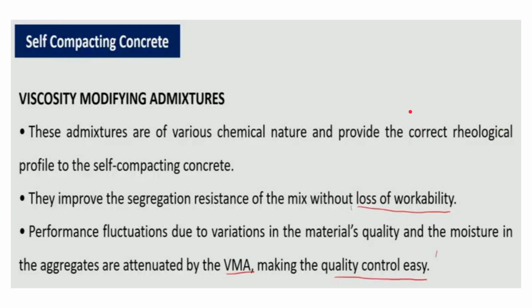Apart from that, let us go through the viscosity modifying admixture. VMA admixtures are of various chemical natures and provide the correct rheological profile to the self-compacting concrete. They improve the segregation resistance of the mix without loss of workability. Segregation resistance is the main job of the VMA. Performance fluctuations due to variations in the material quality and the moisture in the aggregates are attenuated by the VMA, making quality control easy.